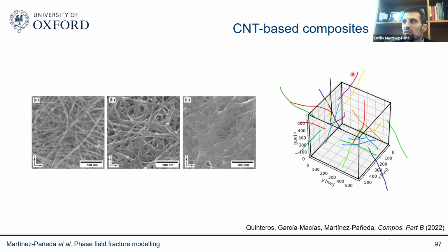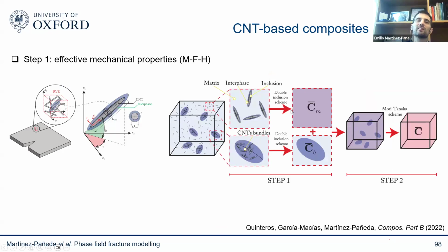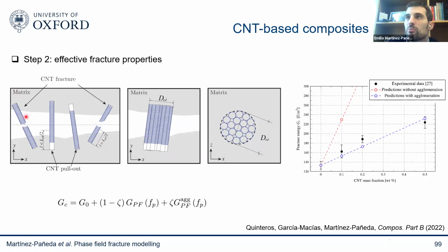And he did that through two classes of models. One where you simulate also the RVEs of the carbon nanotubes, but another one where you homogenize these carbon nanotube composites, because carbon nanotubes are at the nanoscale. So we don't want to simulate things discretely at the nanoscale. So we have homogenization techniques where we capture the effect on the mechanical properties using mean field homogenization, but also on the fracture properties, and how they contribute to preventing crack growth by some sort of fiber toughening effect, but also where you have phenomena such as carbon nanotube pull-out or aggregation of those carbon nanotubes. So again, all captured through the toughness and through homogenization.